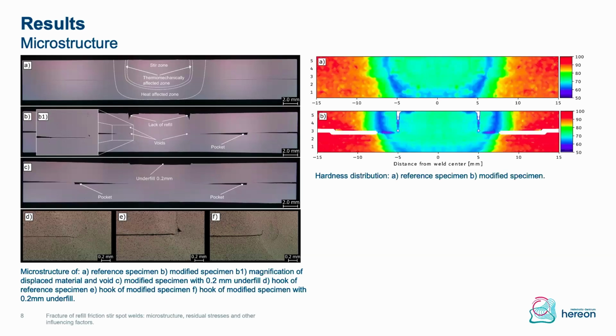Afterwards, we did some hardness measurements to see if we could influence the hardness due to the hot forming process. But basically, we saw that the hardness distribution in the reference specimen, which we see up here, is pretty much the same as in the lower one, except that we have a slightly bigger heat affected zone in the modified specimen, which is also not very good. The white areas you see here correspond to the areas where the pocket is, where we just could not measure any hardness since there's no material available.